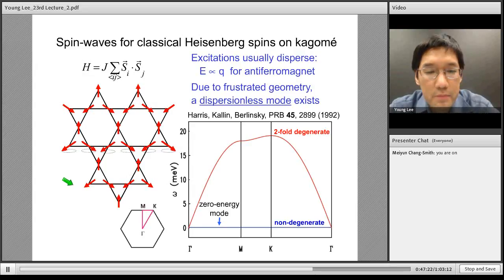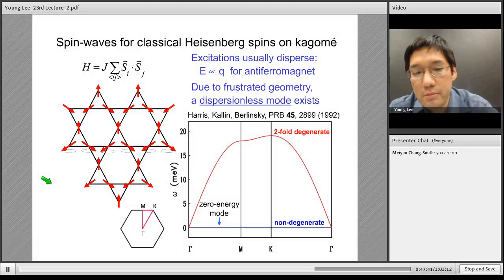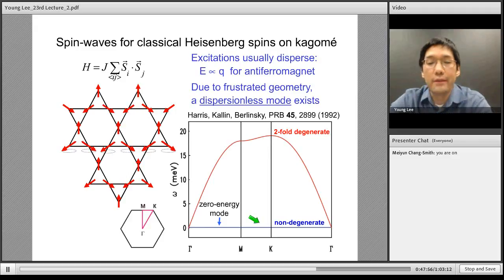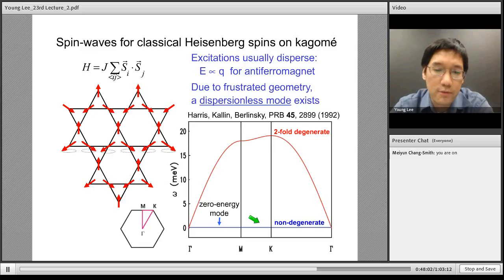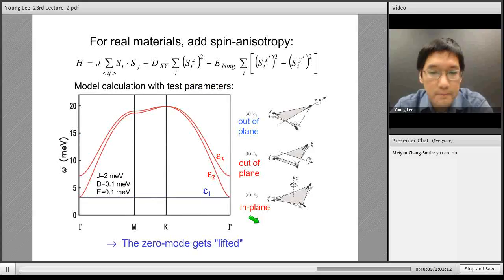However, this line of spins is essentially decoupled from this line of spins because there's just a single vertex shared between plaquettes. So you can create arbitrary wavelength rearrangements along this direction going up and down, and these different wavelength rearrangements don't change the energy, which means that as a function of wave vector, looking at this dispersion, for many different wave vectors, you have the same ground state energy. And that's the origin of this zero energy mode. So this is very unique, and it's characteristic for highly frustrated lattices.